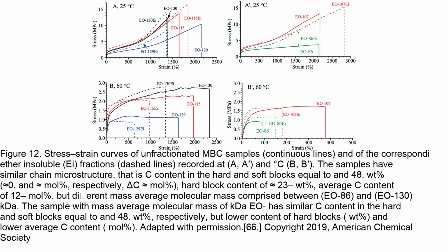ductility at 25 degrees Celsius. However, at 60 degrees Celsius, the MBCs with lower molecular mass and fewer blocks show a significant decrease in ductility. These results indicate that the chain microstructure, including block length and number of blocks per chain, significantly affects the mechanical properties of the MBCs.